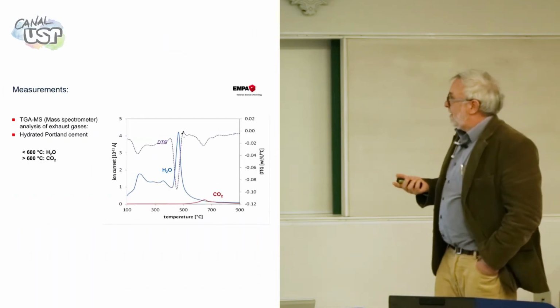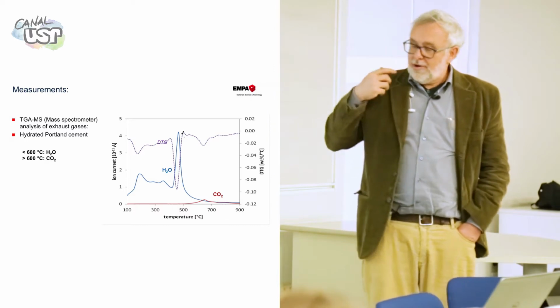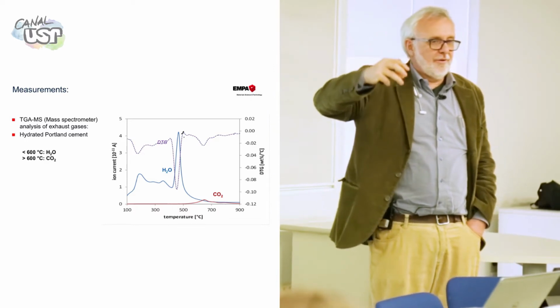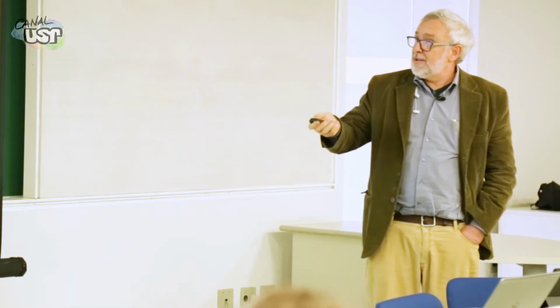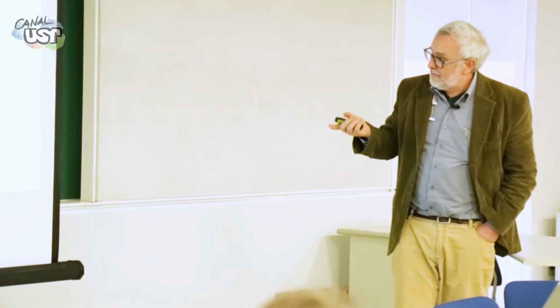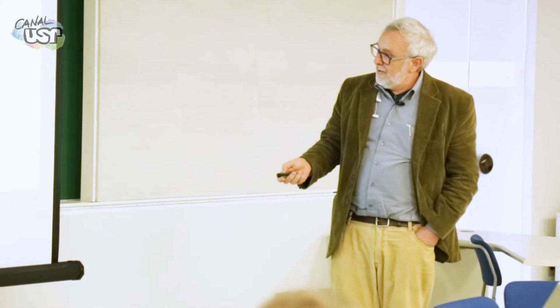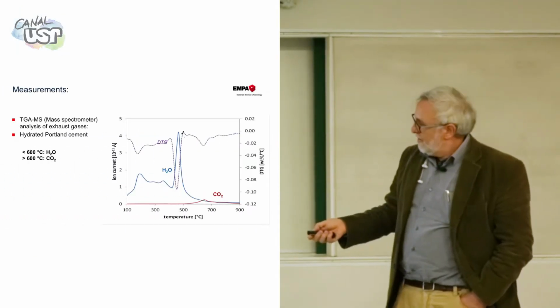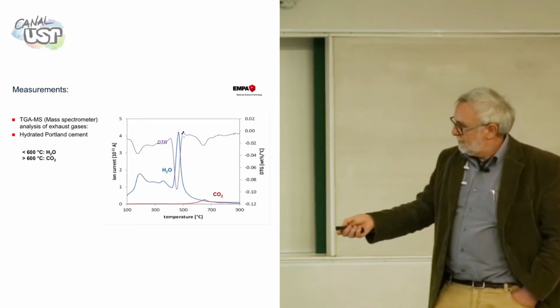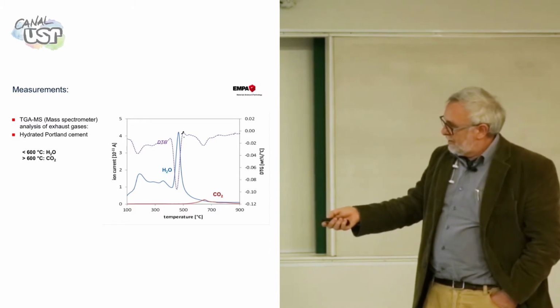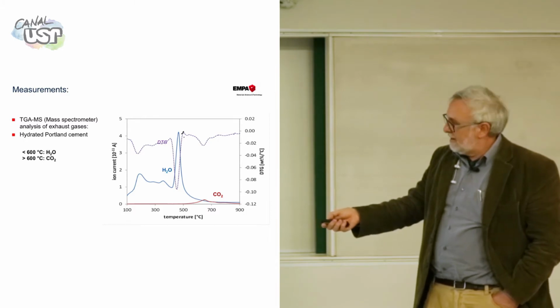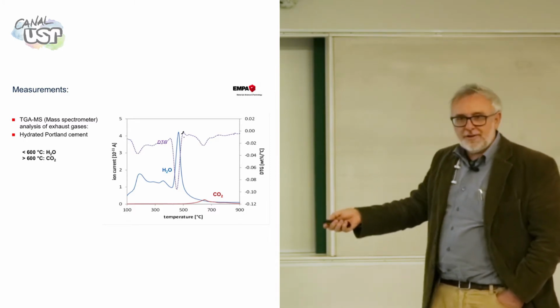A nice thing we can have: if you put a mass spectrometer in the vent of your TG, you can measure the chemical composition of the gas that is coming out of the system. Okay? And so they did this here. They started to heat the sample. In the beginning, 100 degrees, water, zero CO2. Then a peak of water, this is probably CSH and ettringite. Then another peak of water, portlandite decomposing. Very sharp peak, very clear.